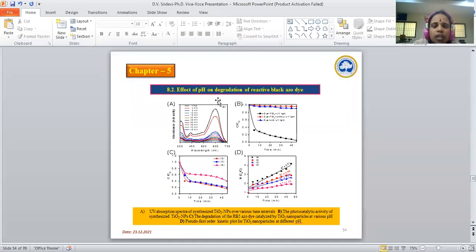This slide shows the effect of pH on degradation of Reactive Black 5. Figure A shows the photocatalytic degradation of RB5, an anionic dye, by titanium dioxide nanoparticles within 45 minutes. When UVA light irradiated the titanium dioxide nanoparticles, 96% photocatalytic efficiency was observed. In figure B, we carried out control conditions in the presence and absence of UV light with TiO2 nanoparticles. In the presence of UV light it shows 96% photocatalytic efficiency, but in the absence of UV light it shows only 16% photocatalytic activity, as shown in figure B.